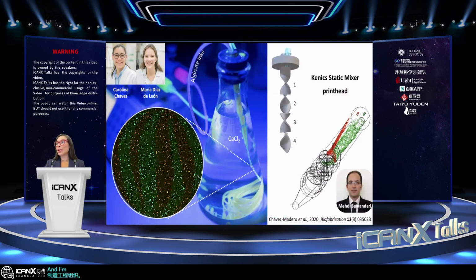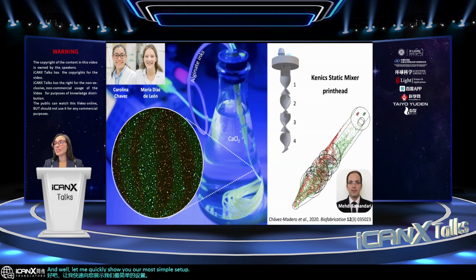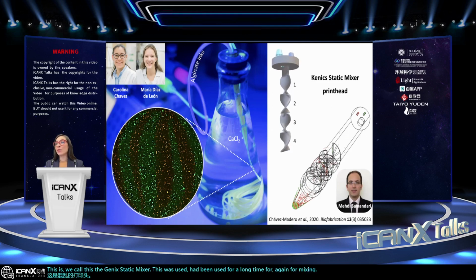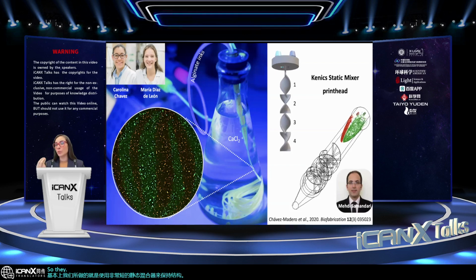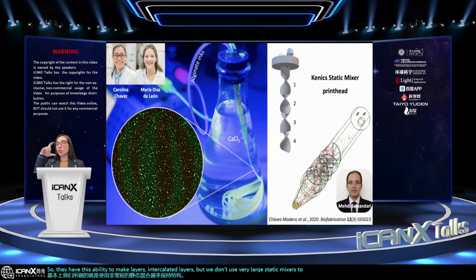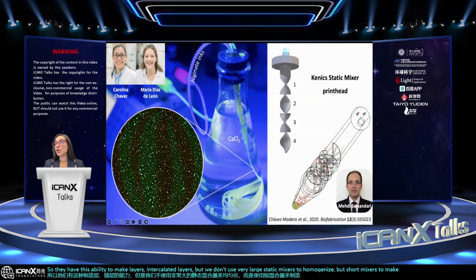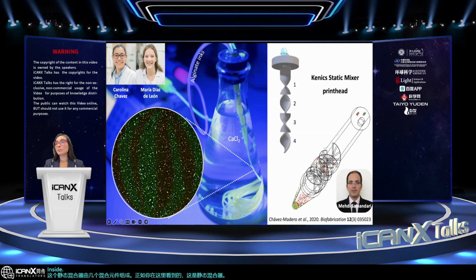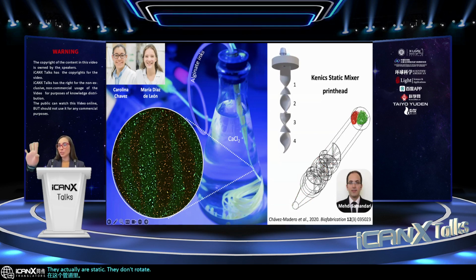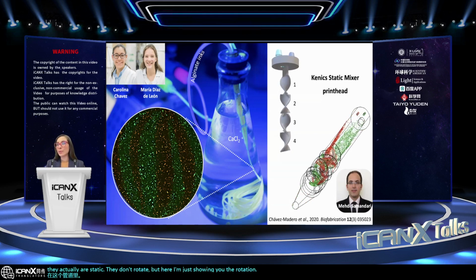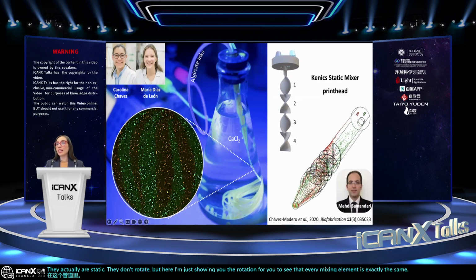And well, let me quickly show you our most simple setup. This is the chaotic printing head. We call this the Kenics static mixer. This has been used for a long time for mixing very viscous liquids. And basically what we do is we use very short static mixers to preserve the structure. They have this ability to make layers, intercalated layers, but we don't use very large static mixers to homogenize, but short mixers to make a structure. And this static mixer is composed of several mixing elements. As you can see here, this is the static mixer that comes inside this pipe. They actually are static, they don't rotate, but here I'm just showing you the rotation for you to see that every mixing element is exactly the same, but they are positioned 90 degrees with respect to each other.